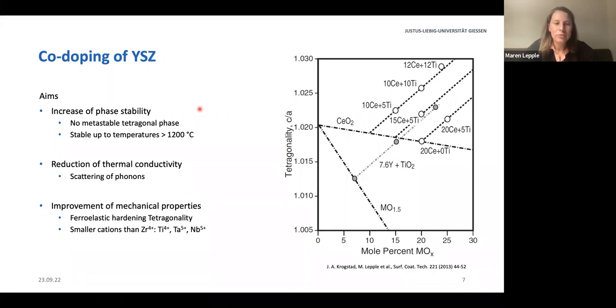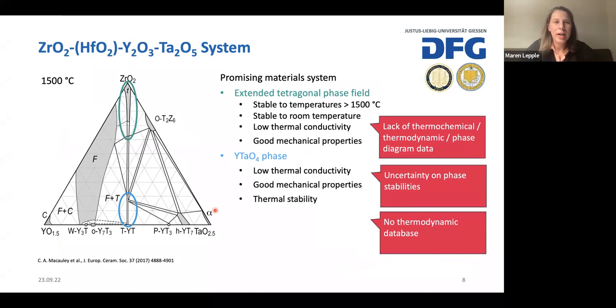And also the mechanical properties can be improved, for example, by increasing the tetragonality, as shown here by the elements cerium and titania. So I investigated the system zirconia-yttria-tantala, which is also a very promising material system for thermal barrier coating applications, because in the zirconia-rich corner here, we have a very extended tetragonal phase field, which is stable to temperatures above 1500 degrees centigrade and stable to room temperature. It has a very low thermal conductivity and good mechanical properties.